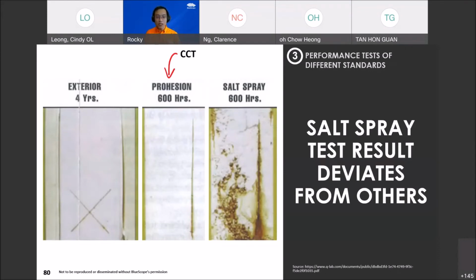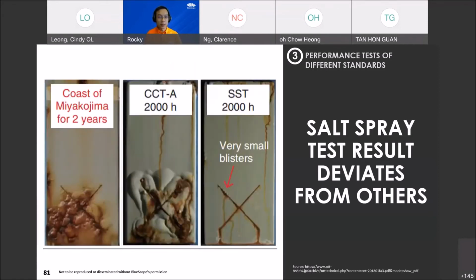So when people see this, right, there is always a confirmation bias that says, oh, does it mean the salt spray test will be much more severe? The result I see will be the worst it can be. If you're just seeing this, right? But if you see more data, it is not always the case. Okay, so this is research that I extracted from one of the Japanese research papers. On the left is the outdoor exposure again, cyclic corrosion in the middle, and salt spray on the right. And what you can see from here is that outdoor exposure of 2 years, near the coast, yielded more severe results compared to salt spray.